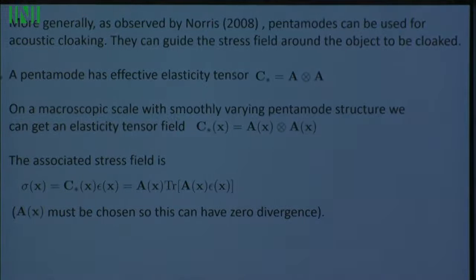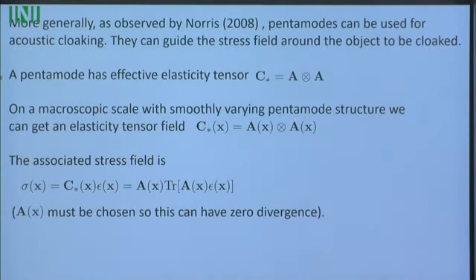So actually, as observed by Norris, pentamodes can be used for acoustic cloaking. They can guide the stress around the object to be cloaked, even for acoustic waves. A pentamode has an effective elasticity tensor which is a rank 1 tensor. On a macroscopic scale with smoothly varying pentamode structures, you get an elasticity tensor field of this form, and the associated stress takes this form here. This is somehow analogous to pressure in the material, and so the stress is everywhere proportional to A of x, and of course A of x must be chosen so that the stress has zero divergence.